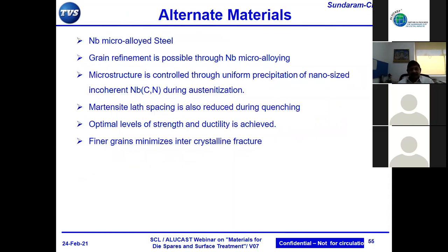And other materials that are coming, the steels that are becoming more and more popular are the niobium microalloy steel, where it gets really good refined grain, so that you have a much higher toughness, and heat checks are much lower here. And nanomaterials are coming in with niobium and carbon and nitrogen intermetallic nanomaterial doped steels are coming. And these are some of the new materials that are coming with different features.